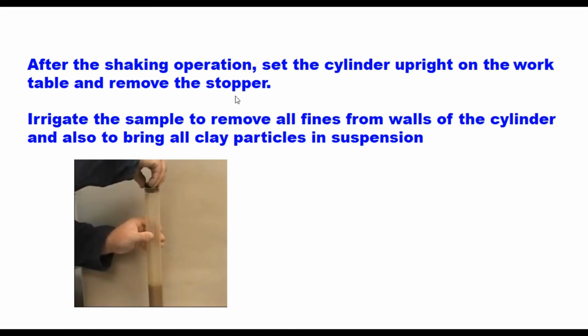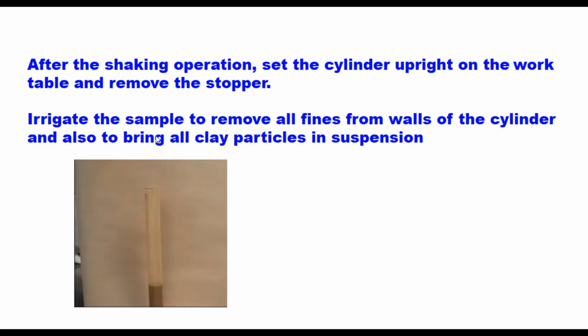After the shaking operation, set the cylinder upright on the work table and remove the stopper. After removing the stopper, irrigate the sample to remove all fines from the walls of the cylinder and also to bring all clay particles into suspension. Raise the irrigator slowly without shutting off the flow so that the liquid level is maintained at 381 millimeter, that is 15 inch, while the irrigator is being withdrawn.